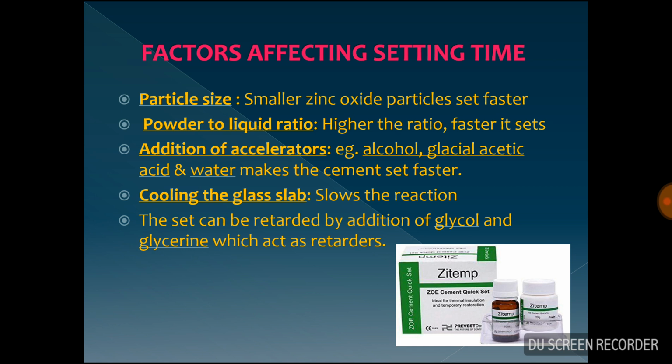Factors affecting the setting time. Particle size: smaller zinc oxide particles set faster. Powder to liquid ratio: the higher the powder to liquid ratio, the faster it sets. Addition of accelerators: accelerators like alcohol, glacial acetic acid, and water make the cement set faster.